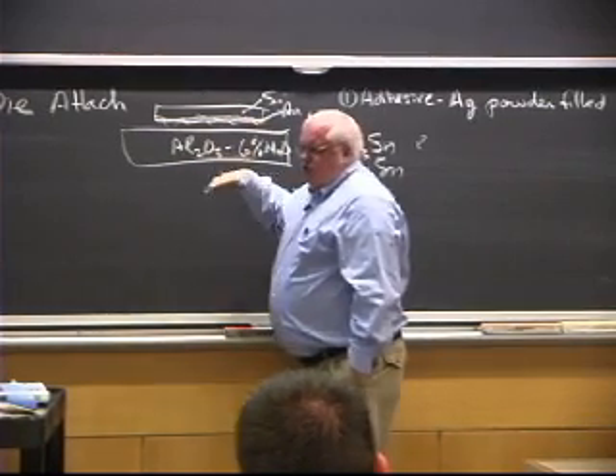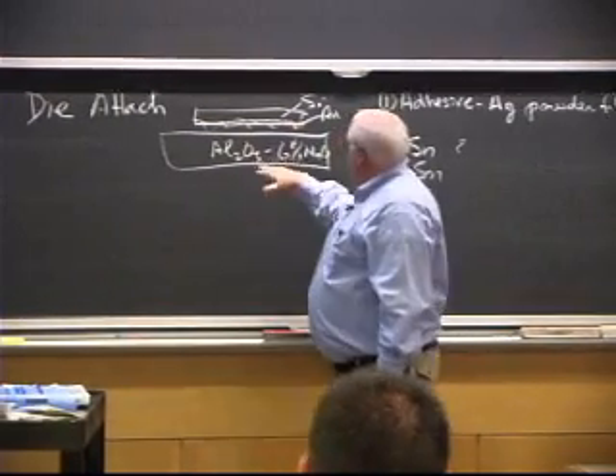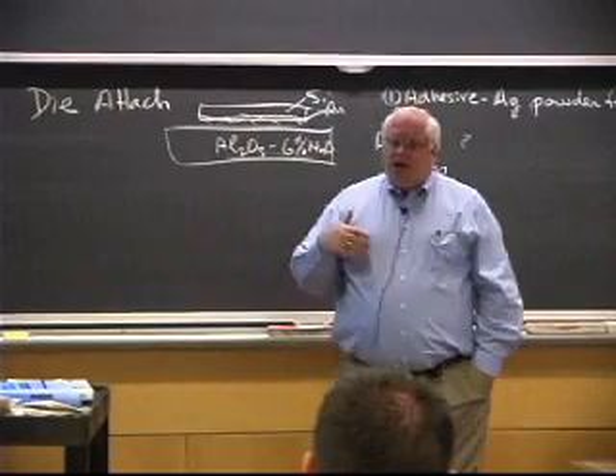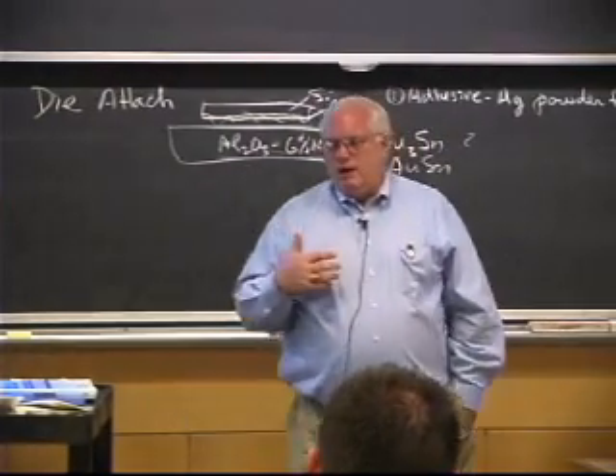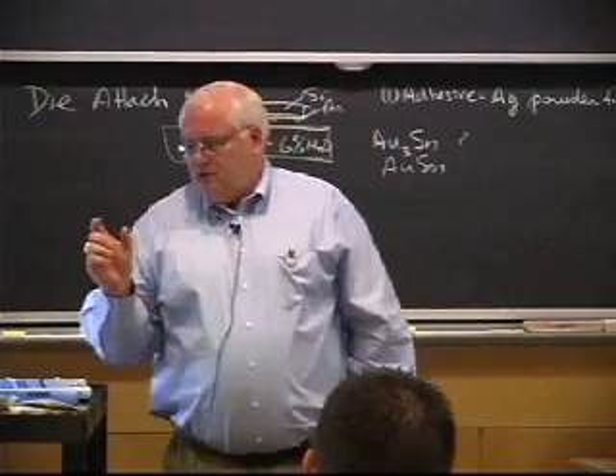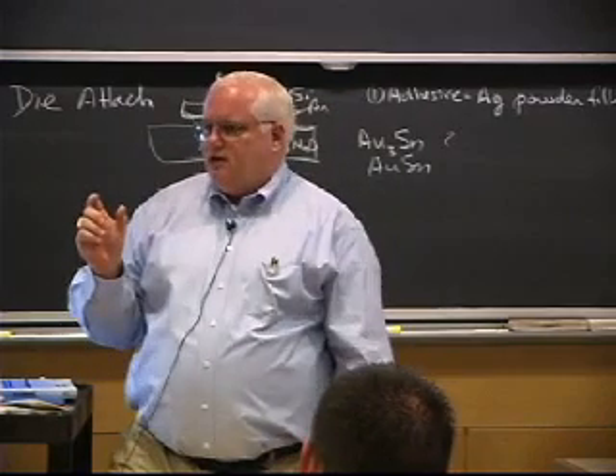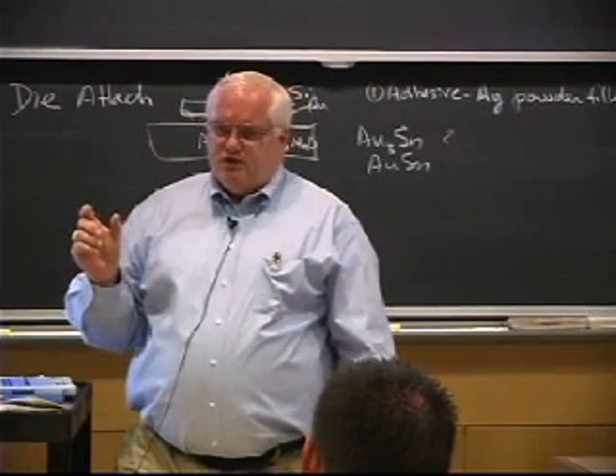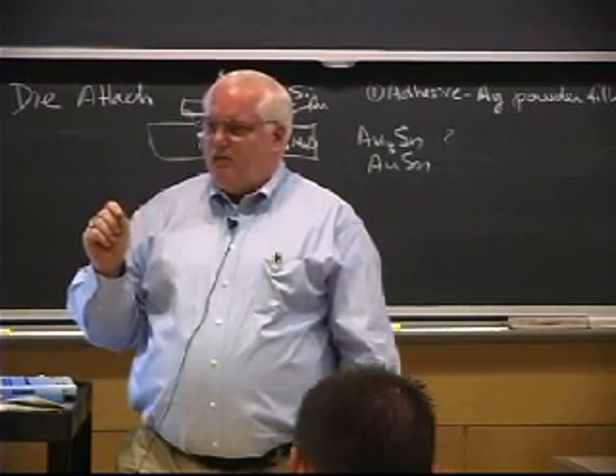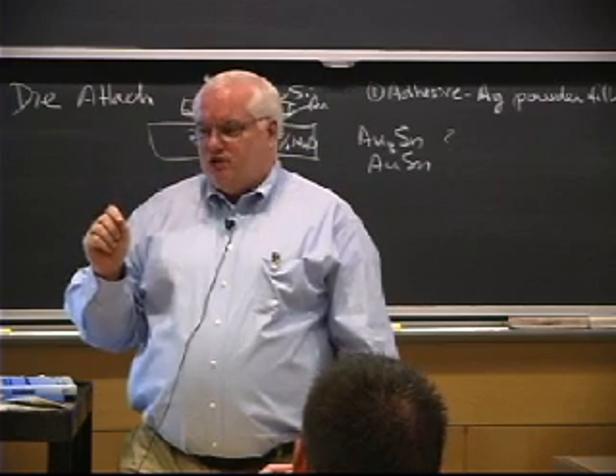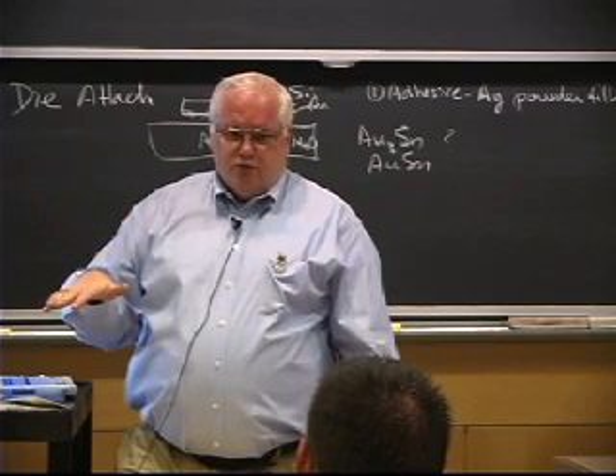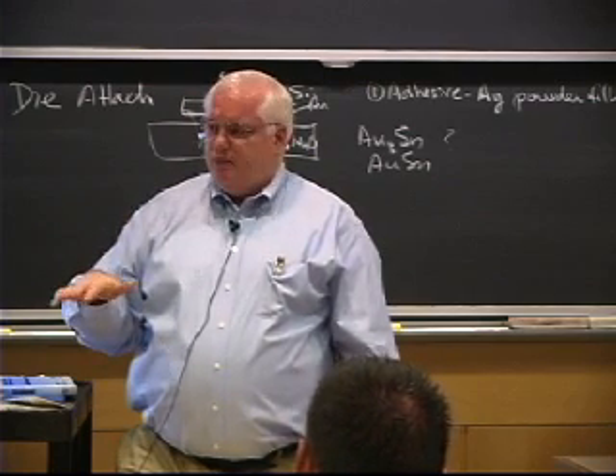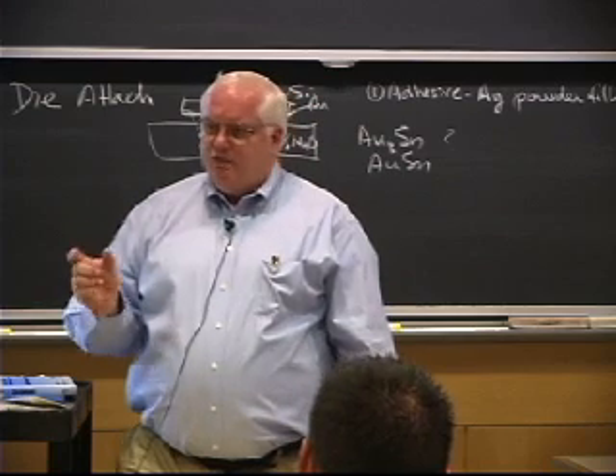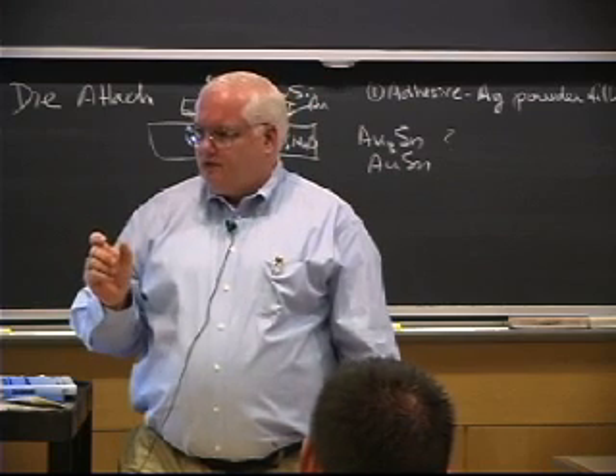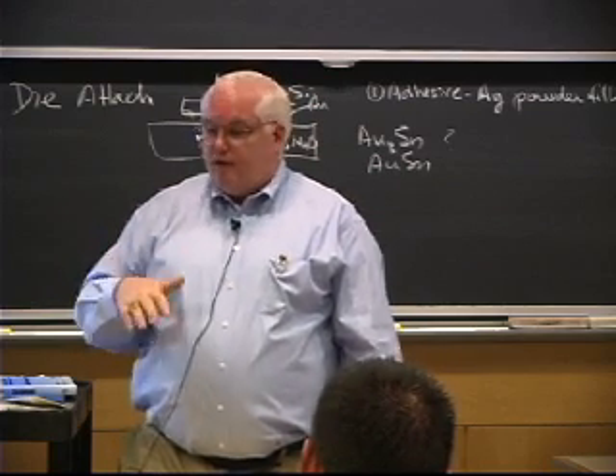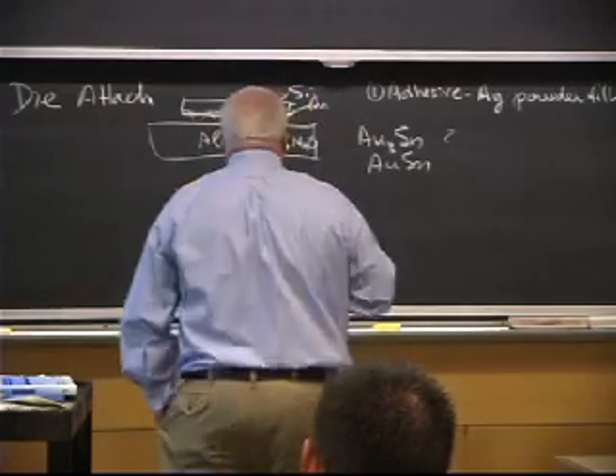And so you can't just use straight Al2O3 with manganese oxide. You usually have to use something like, nowadays the fancy thing is an aluminum metal matrix composite. It's basically silicon carbide at about 60 volume percent infiltrated with aluminum. So it's an aluminum metal matrix composite, and it matches the coefficient of expansion very, very closely. And so you don't have a problem of breaking the chip from thermal expansion stresses.